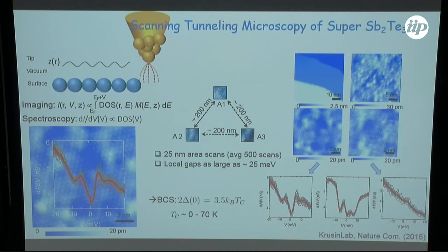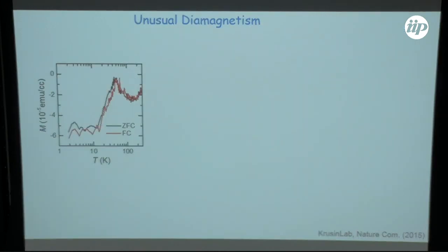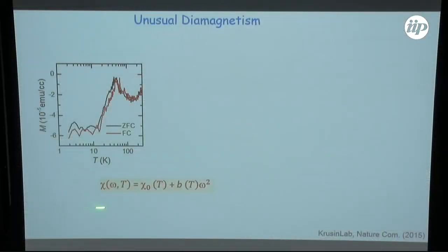But that convinced us that we have some sort of a puddle system, a mesoscopic superconducting puddle system. Furthermore, if we looked at the magnetic response, or what I would call the mesoscopic Meissner effect, this is actually DC SQUID measurement, the big change. This is not 1/4π, it's clearly much less here because the system is sparse. It's also around 60 Kelvin, and if we look at the AC susceptibility, we can beautifully fit it